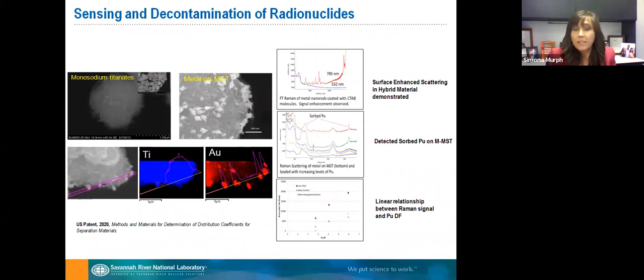How did we actually implement it at the site? Of course, working with radionuclides, you always have to use sorbents to actually capture the radionuclides. Once you get these materials to absorb the radionuclides, you never really know if we still have some extra radioactive material in the tank. How can we really know? We have to take a small sample, we have to package these materials, we have to put it on the road, we have to take it to the lab. So it's a very complex process that is laborious, and it takes a lot of steps. So we proposed, why not use these gold nanostars as a reporter tag to really test to see if we still have this radioactive material in there. So that's what we did.